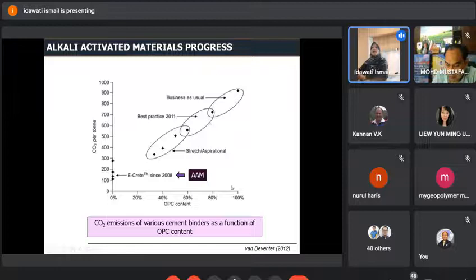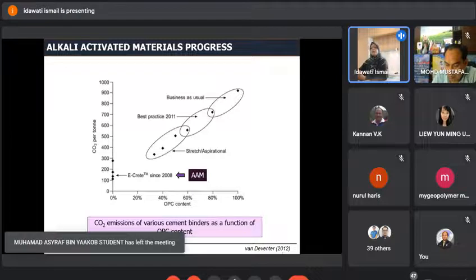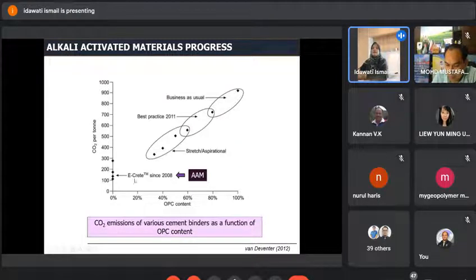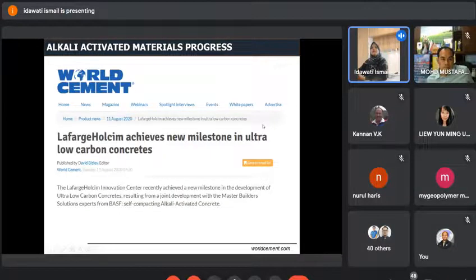And where is the progress now? This is if you use zero OPC, okay, the CO2 emission. This is from van Deventer's study. van Deventer has a product called E-Crete, which uses slag system and fly ash system with zero OPC, and they found that the CO2 emission is lower than 100% OPC. So it is an inspiration. It is motivation to, how do you say, contribute to environment protection.